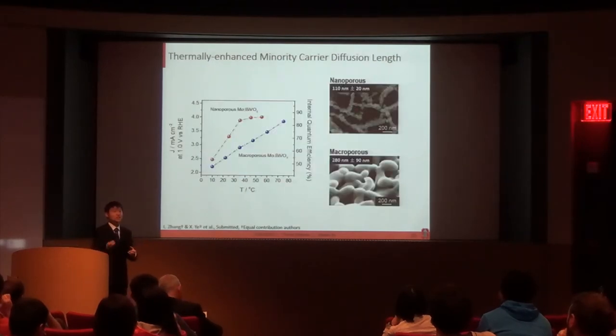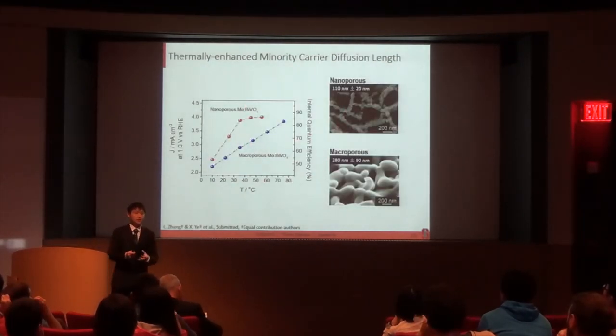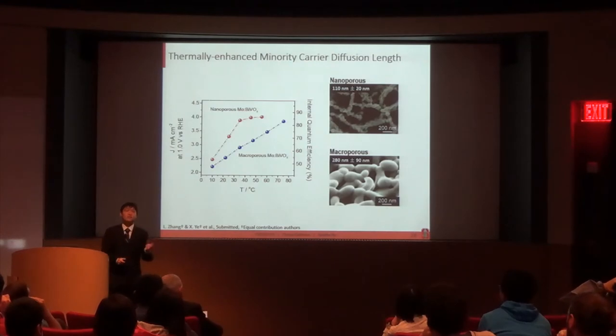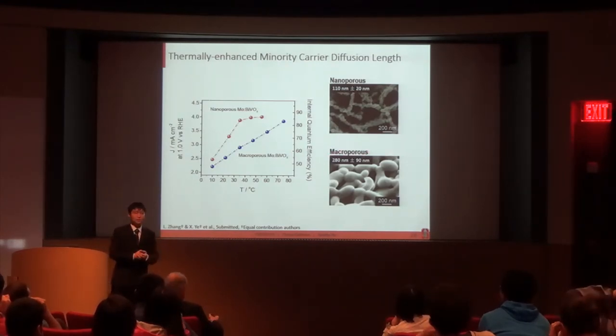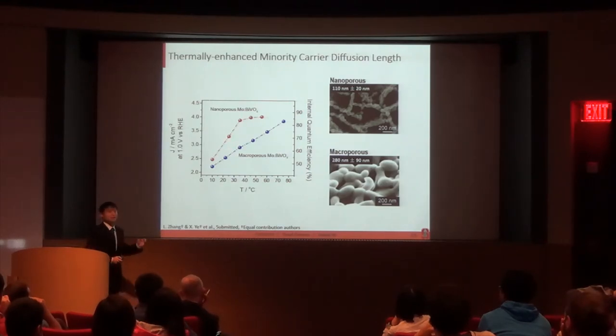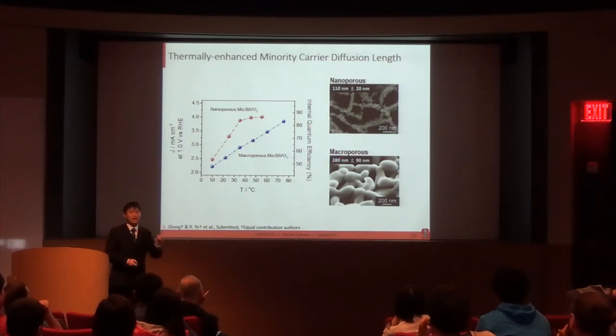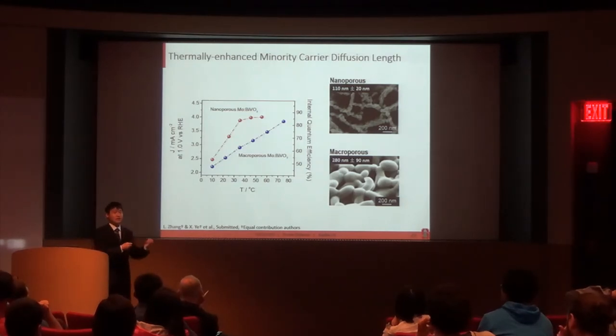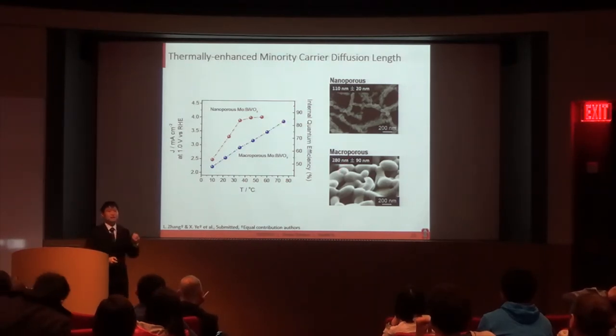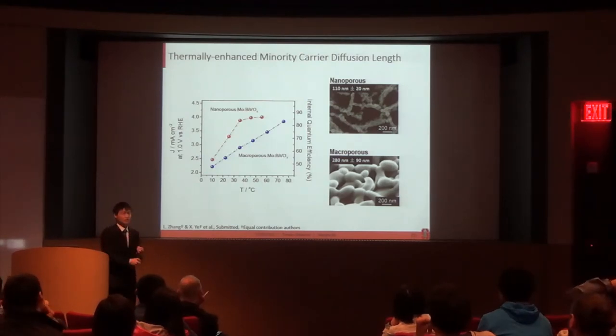So in order to provide additional evidence on the thermally enhanced minority carrier diffusion length, we compared the photocurrent in two different BVO photoanodes with different particle sizes, the nanoporous and macroporous BVO. For the nanoporous BVO, you can see that the photocurrent increases strongly with temperature and soon reaches a plateau at around 35 degrees Celsius. While for the macroporous BVO, the photocurrent starts at a low value and rises at a slower rate. This is probably because of the smaller surface area to volume ratio in this macroporous BVO. But it continuously increases at almost a constant rate all the way to 80 degrees Celsius, which is the highest temperature we can achieve in our experimental setup.